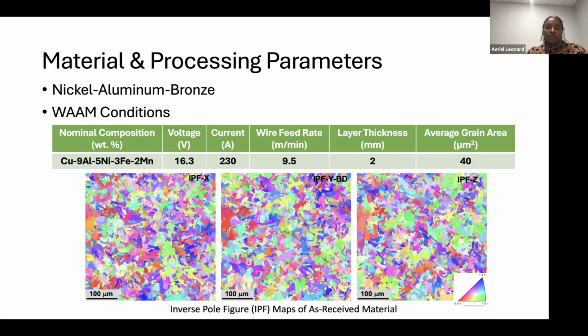It is well known that you can get varying microstructure along the bar, especially along the thickness of the layers. So we take most of our samples in the center of every bar because we know that the microstructure is pretty consistent in that region. It's really about keeping track of what microstructure we're looking at as we're doing mechanical testing.